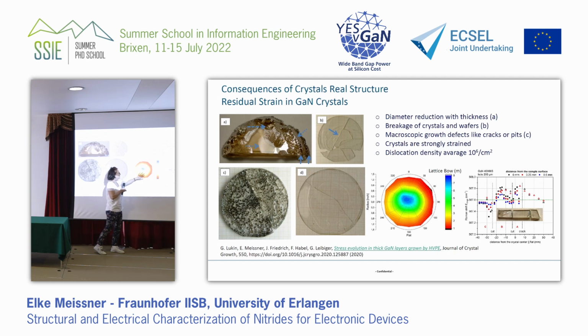So for crystal growth, you have to control the growth environment, or the growth condition, I would say, over a large area in a furnace, which is the size like this. You grow a crystal like this, but you have a furnace like this with gases flowing here. You have to control them atom by atom, so it can be very much uneven. So growth thickness can be uneven, then the crystal will be bowed and strained. This is what we monitor, for example, with Raman spectroscopy. So we apply Raman spectroscopy, and we make mappings over the cross sections of the crystal, over the whole crystal area, such that we know what properties the crystal has in terms of the atomic arrangement.